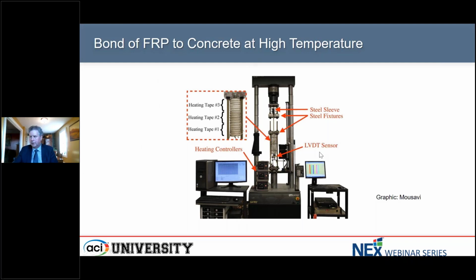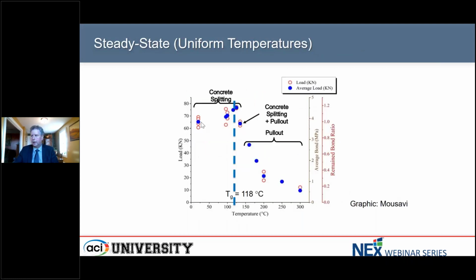We initially looked, these are some tests that we've done more recently in our high temperature furnace, and now we're looking at longer lengths of GFRP bars embedded into concrete, and we've wrapped these with heating tapes such that we can control the temperature in 3 different zones in this case. So what we found here is that we did some tests in different regions, and we found that when we have steady state uniform temperatures, that we are getting falling off at temperatures that are above the glass transition temperature, as we found for shorter lengths as well.